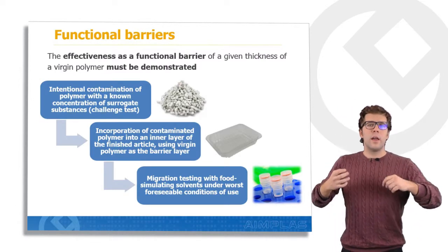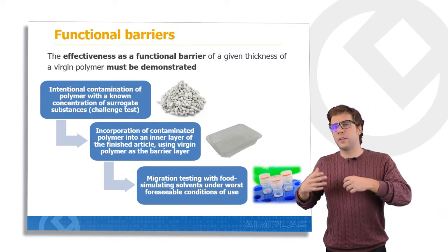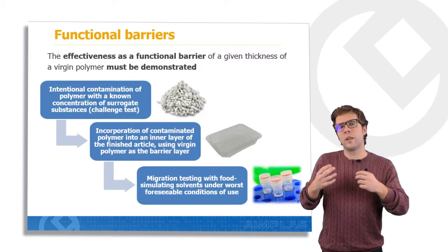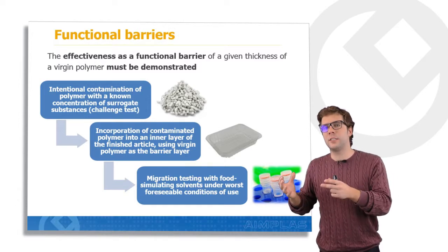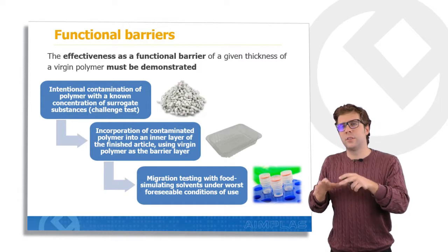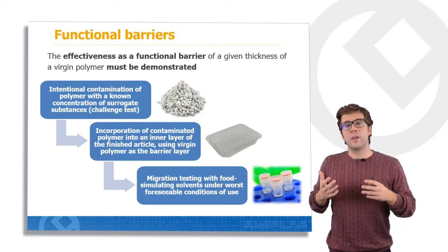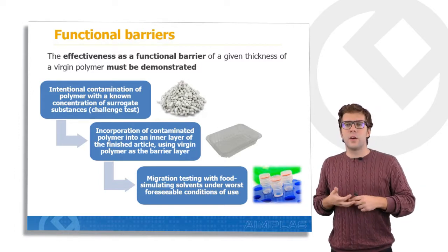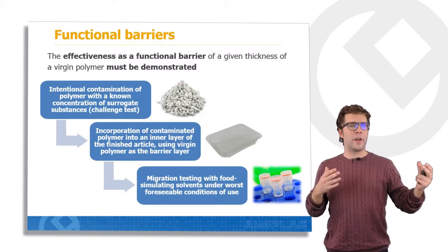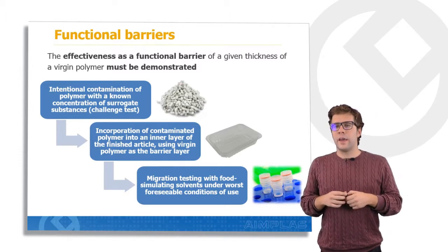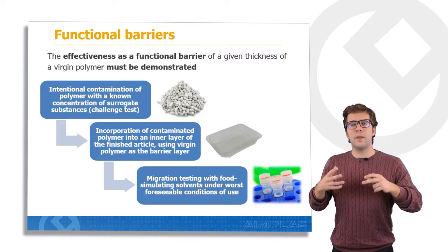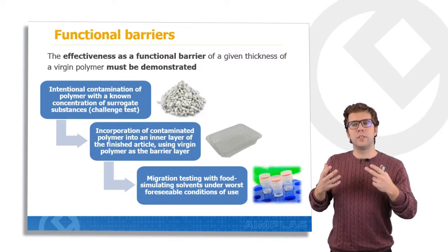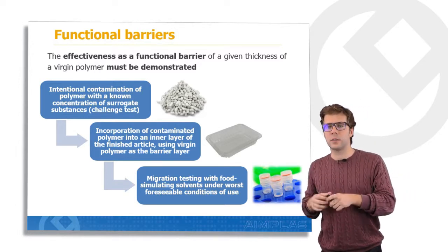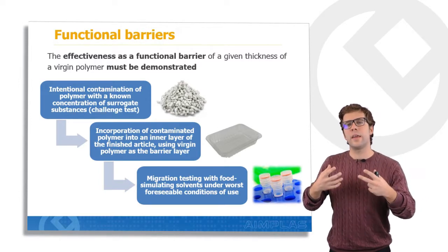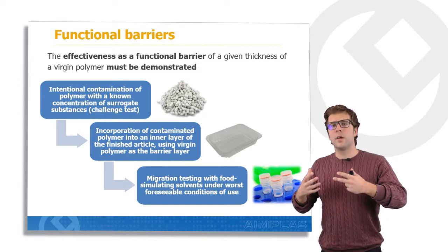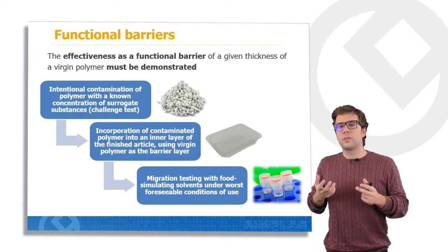But as I said before, if there is no scientific evidence on the effectiveness of the functional barrier, we demonstrate this effectiveness case by case, because of the different parameters that could affect it. The method that we use in AIMPLAS to demonstrate the effectiveness of a virgin polymer with a given thickness as functional barrier for other polymers or even for other materials is the following. First of all, we contaminate the virgin polymer with a known concentration of surrogate substances, what is known as a challenge test, and we use this polymer to simulate a recycled plastic in the worst scenario possible, with the highest concentration of pollutants.